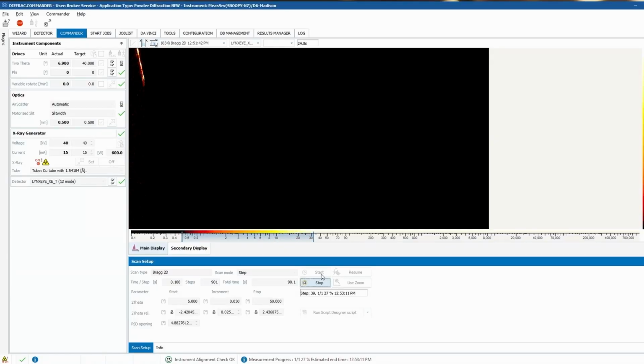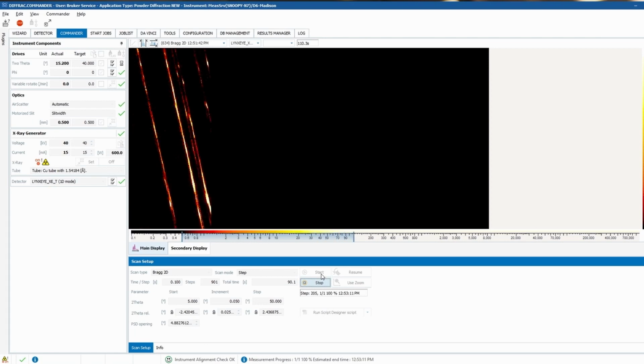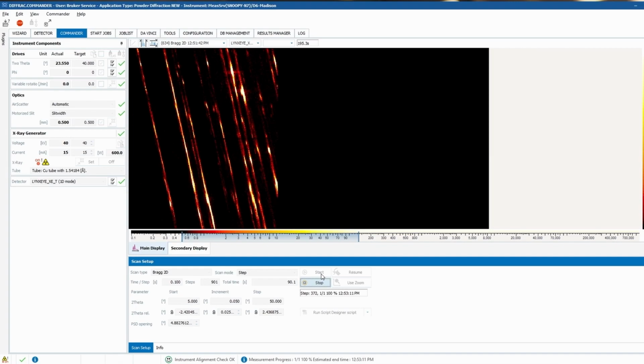Another unique powder measurement to Bruker solution is called BRAGG2D. In BRAGG2D, the full divergent beam geometry is used in combination with a 1D detector to collect a two-dimensional diffraction scan. This allows quick identification of sample preparation issues, such as preferred orientation and large crystallite size, which may affect the relative intensities of peaks in the 1D data. The power and versatility of the D6 phaser allows powder X-ray diffraction to go beyond basic scan.